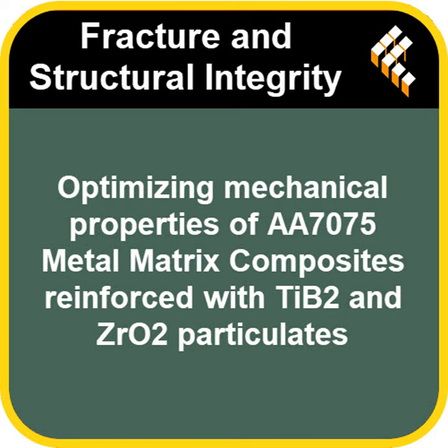Right, so tensile tests measure that. We often look at yield strength, the point where the material starts to deform permanently. The original as-cast AA7075 alloy has a yield strength of roughly 107 megapascals, or MPa. 107 MPa. Again, the 5% TiB2, 4% ZrO2 composite came out on top. Its yield strength was 123 MPa. Okay, so that's about a 15% increase. Still significant, but not as dramatic as the hardness jump.